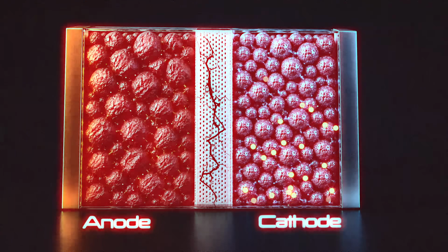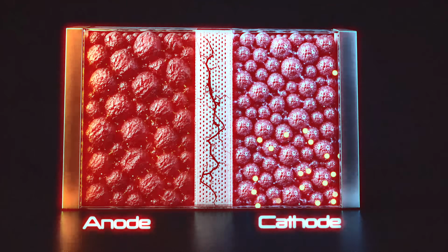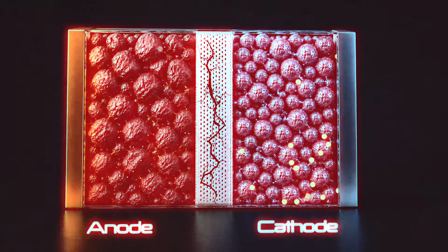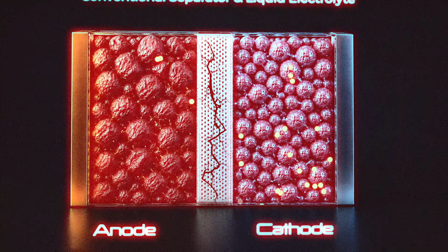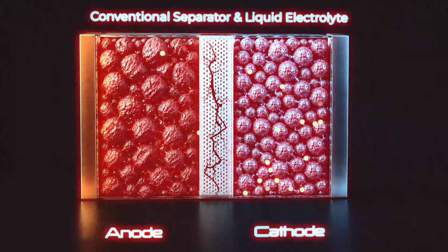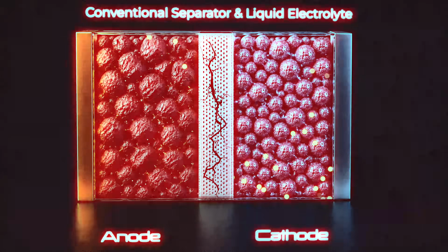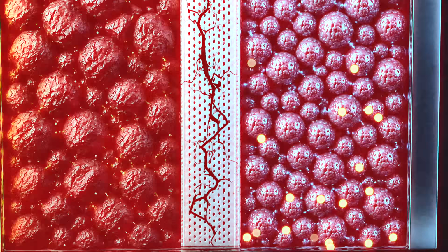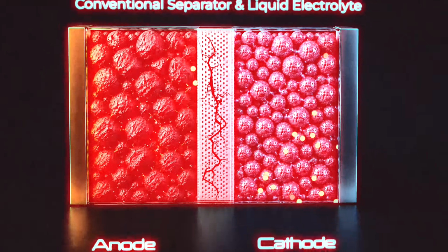Once it starts, you can't really stop it. The cell heats itself, vents, and burns until everything reactive inside is gone. That's thermal runaway, and it's why a single bad cell in an EV pack can take down the entire vehicle. Conventional batteries fight this with one tool, that thin plastic separator that physically keeps the cathode and anode apart. The problem is that plastic melts at 130 degrees C, and thermal runaway kicks in at 150. So the defense doesn't survive long enough to do its job.